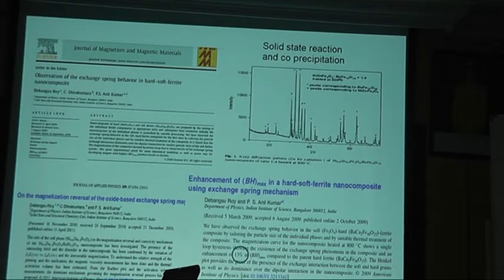They prepared them separately, and then combined them using the mass ratio. They take around 1 to 5, and then they claim they got the exchange coupling. Okay, this is the XRD. From these XRD peaks, we can see they managed to get two phases, nickel zinc and barium ferrite. They claim there are no impurities, so the only peaks belong to barium ferrite and nickel zinc ferrite.